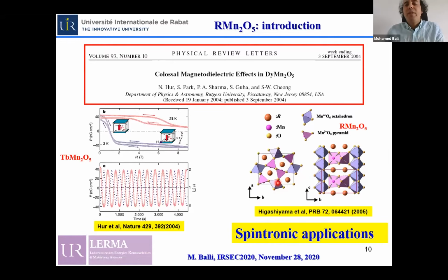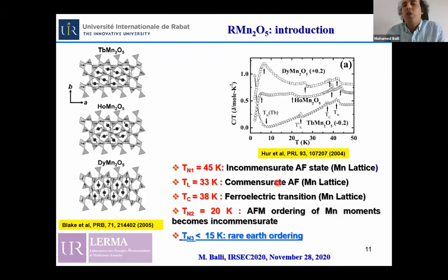It is worthy to mention that the competition between different exchange interactions in this compound, involving both rare earth and manganese lattice, leads to a wide variety of phase transitions, as can be clearly seen in these figures representing the specific heat as a function of temperature.